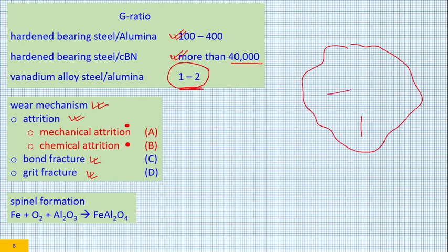This is a grit, and this would be grinding the material. As it grinds, a small wear flat will start developing, and this wear flat develops because of slow removal of grit due to microfracture.